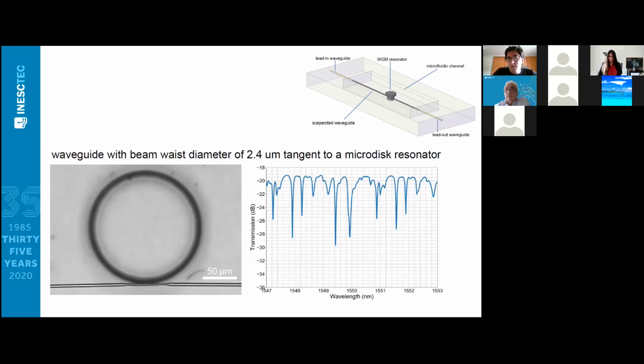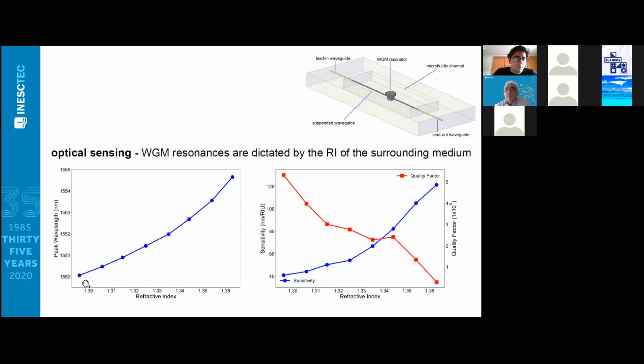Here you have an image of the transmission spectrum where you can see that we have very sharp resonances that are associated to a quality factor of around 100,000. And so this is what we are interested in, particularly in optical sensing applications. We have a very low limit of detection. Here we have the results we have gathered so far related to optical sensing.